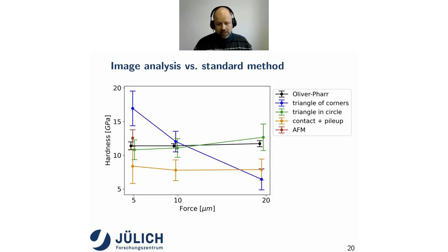And it turns out, and that was also surprising for me, that the triangle in the circle is the best approximation. It is not perfect. It has a larger scatter than the measurements by the conventional Oliver-Pharr method, but it's already in the right ballpark. And for the first measurement of the system without any calibration, we were pretty happy with it.